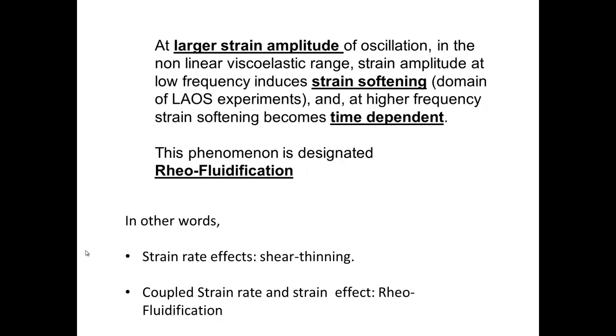At larger strain amplitude, for instance, of oscillation, suppose I'm oscillating the melt, say transversal to its flow direction. We will see that in a couple of slides, the way I can do that. But at larger strain amplitude, so-called in the nonlinear viscoelastic range, the strain amplitude at low frequency induces strain softening, which is the domain of the large amplitude oscillation experiments, typically 1 Hertz.